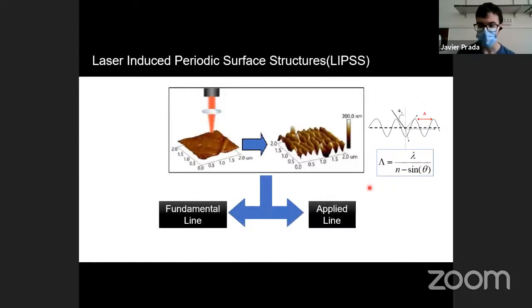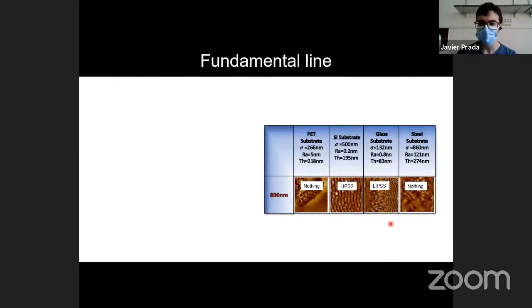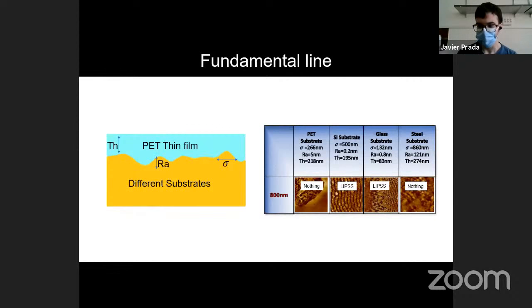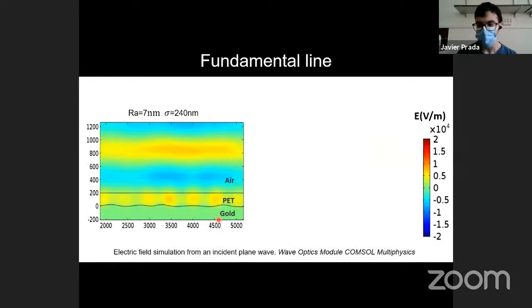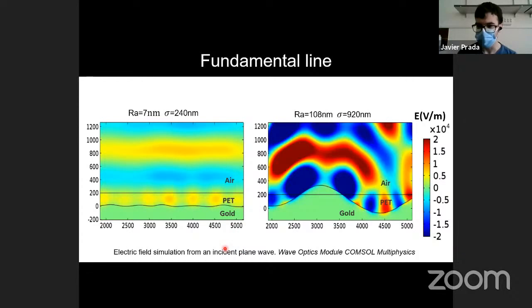My work can be divided into two major lines: a more fundamental line where I try to understand the formation mechanism of LIPSS, and a more applied line where the interest is in the property changes brought by LIPSS and their possible applications. Regarding the fundamental line, we made an experiment where we studied the formation of LIPSS in thin films of a polymer deposited on different substrates. We found that LIPSS only form for the silicon and glass substrates, but they wouldn't form for the polymer substrate or the steel substrate. To check what influence the thickness of the thin film and the roughness of the substrate had in this phenomenon, we simulated the electric field via finite element methods, finding that indeed the roughness of the substrate and the thickness of the thin film can have strong influence on the formation of LIPSS and their characteristics.